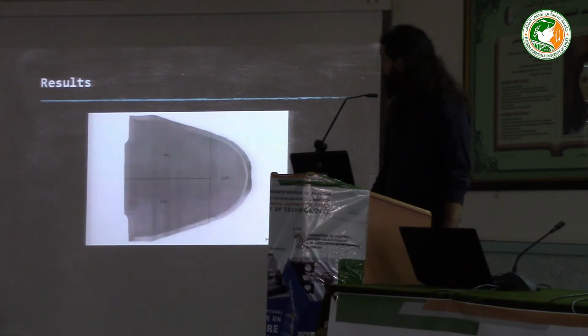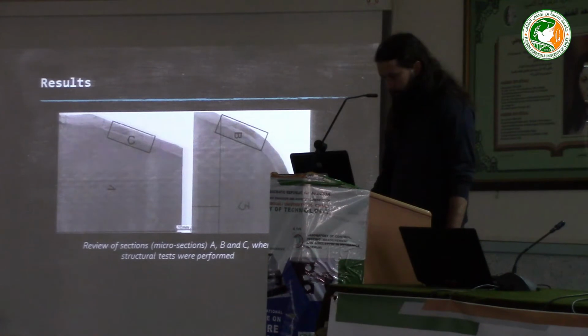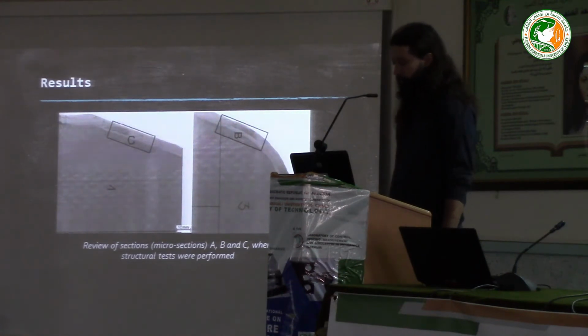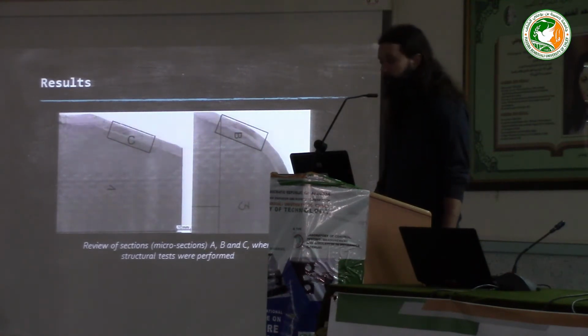The zones denoted by 1 through 3 were used for macrostructural analysis. Now, of more importance to us was the microstructural analysis, and for this purpose, 3 sections were defined, A, B, and C. Section A, as can be seen, is located on the top of the tooth, whereas section B is also located close to the top but on the side. Section C is located in approximately the central part of the tooth. These sections were chosen based on the content of tungsten carbides to see how their presence would affect the amount and distribution of cracks.